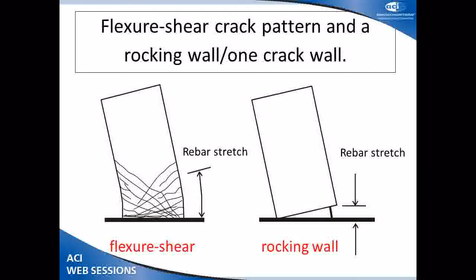What we're expecting from all of our studies and from good, well-detailed walls in the field is a spread fan pattern of cracking, flexure shear cracks, which distributes the stretch of the rebar up a reasonable height of the wall. What we are actually getting, and have seen in numerous buildings, I've personally seen four, I know of at least another five in Christchurch, is that the walls, though they're designed for flexural yielding, actually only split at one crack, typically the construction joint above the beam or the foundation, and all the bar stretch was concentrated at that one crack.